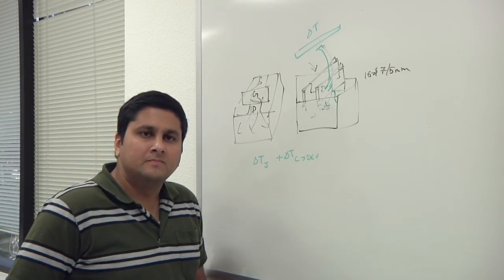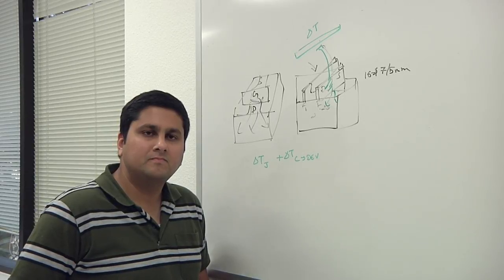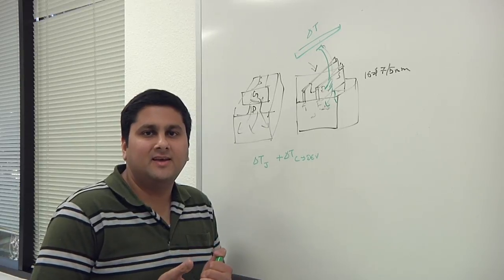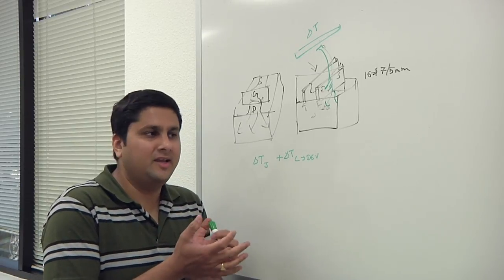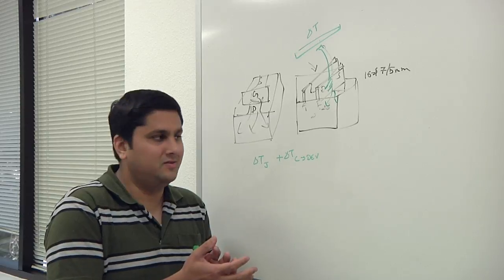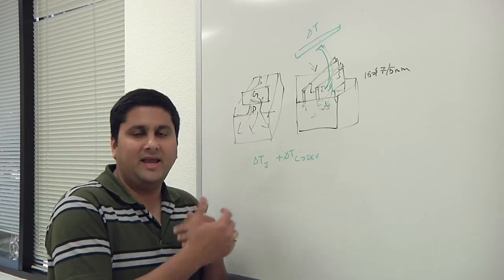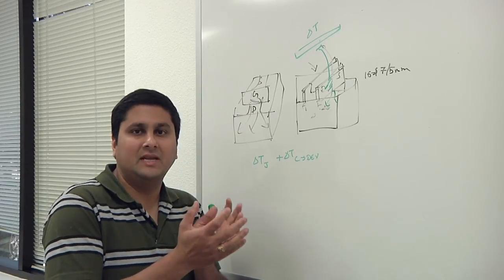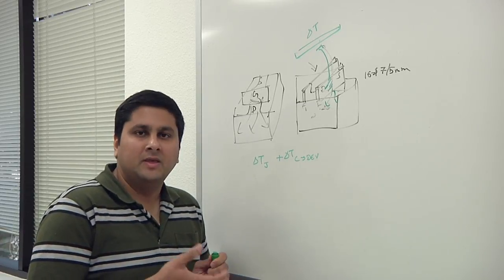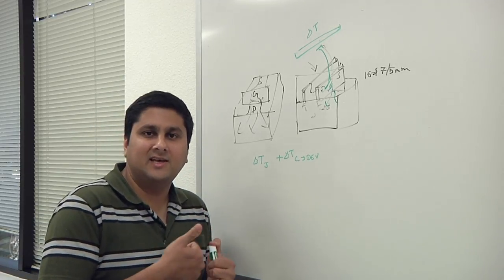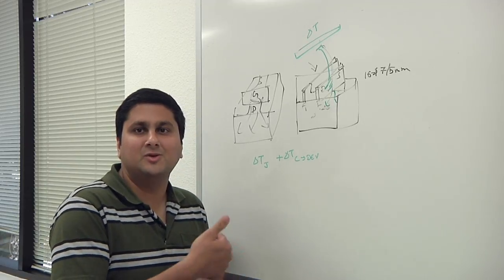So how does this actually play out? So reliability is a word that we're all used to in electronics when it doesn't work, but this isn't necessarily it doesn't work, it just doesn't work 100%, right? Yes. So reliability inherently is of a statistical nature. The EM limits that you typically get from the foundries are assuming that there is a 0.1% failure rate over the operation time of your SoC, which is say maybe 5 years rating or 10 years rating. You get a current limit on the interconnects with the assumption that there is a 0.1% failure rate, which is inherently more like a statistical number. So taking that statistical impact, just because you have one interconnect that has an electromigration failure, it does not mean your SoC is going to be useless.